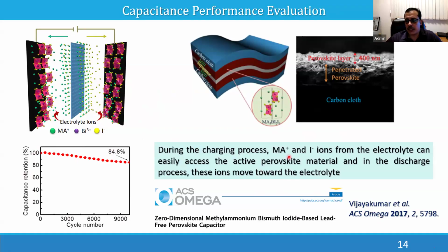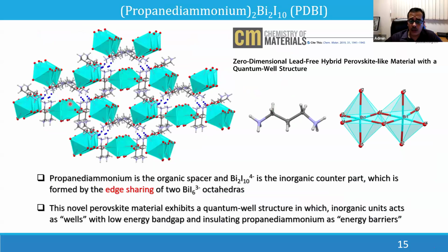So basically, in the charging process, the methyl ammonium and the iodide ions from the electrolyte can easily access the active perovskite material, and in the discharge form, it will go back to the perovskite structure, and it is stable also. So in the next stage, we moved to a slightly bigger organic cation. Instead of methyl ammonium iodide, which is the smallest organic cation, we moved to the propane diammonium cation, that is slightly bigger, and it has two sides. Two sides can bind with the octahedral structure.